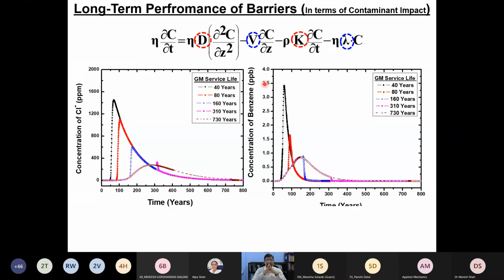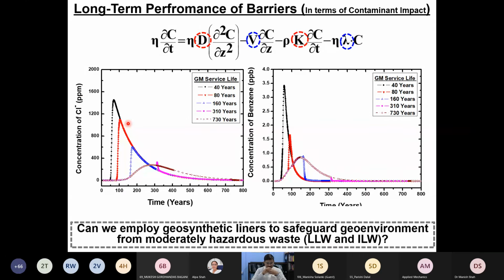And then by knowing all these parameters, mathematically, I can back calculate what happens to the concentration of the chloride, what happens to the concentration of the benzene if the geomembrane service life is varying anywhere between 40 years to almost 730 years. Now you can see very clearly how the service life predictions we made from understanding the mechanisms of aging phenomena, we then transformed in terms of the contaminant impact point of view. So by using this study, you can really say that if the geomembrane fails within 40 years of installation, the peak concentration of both benzene and chloride is really changing. So this is what exactly we have to do.